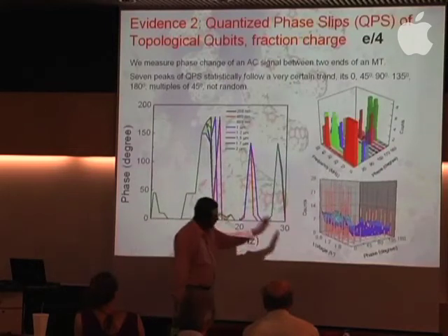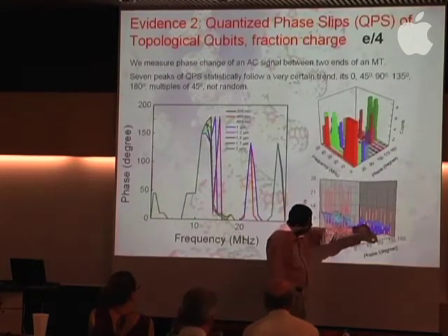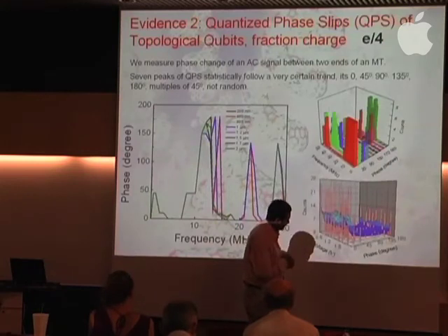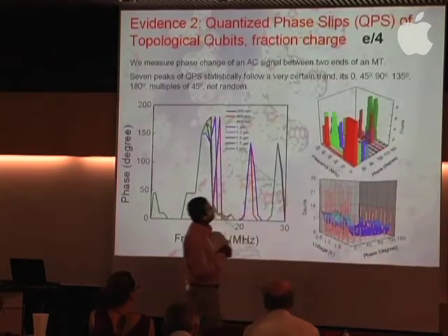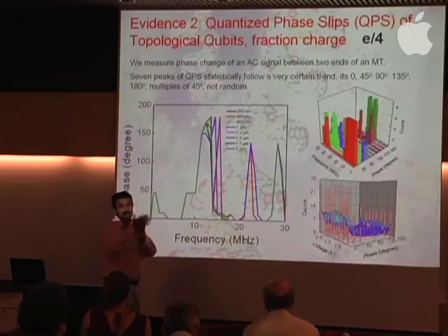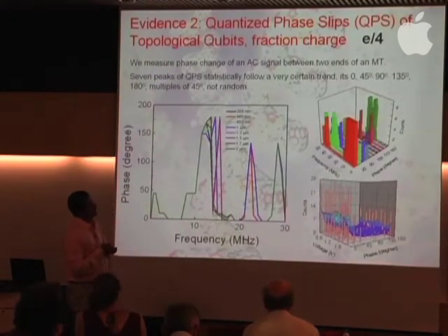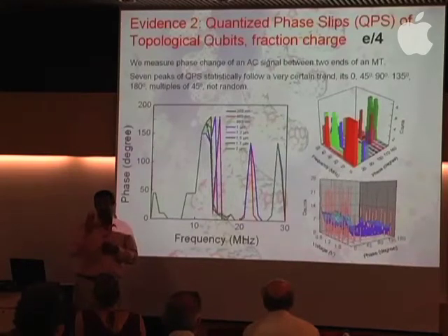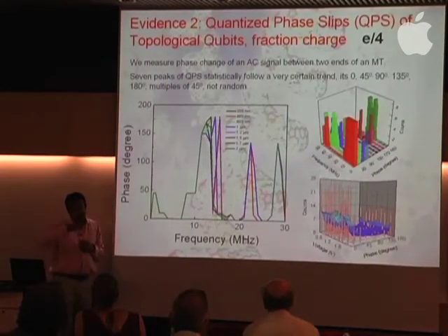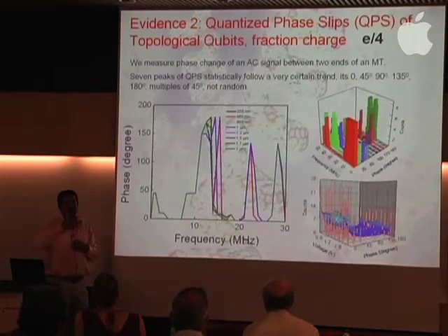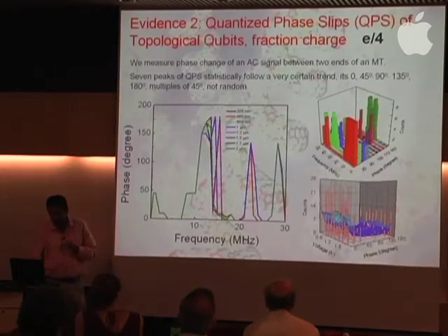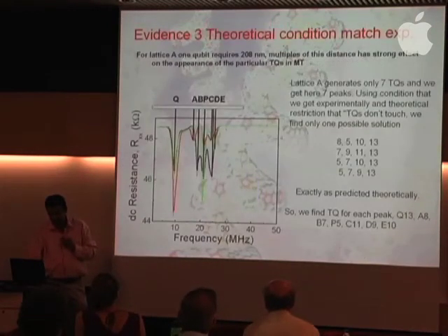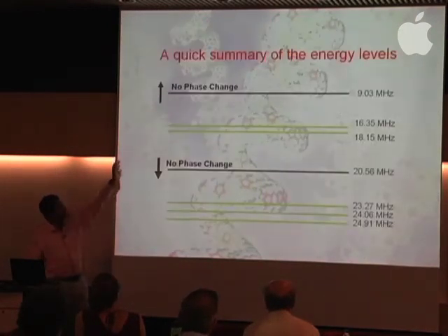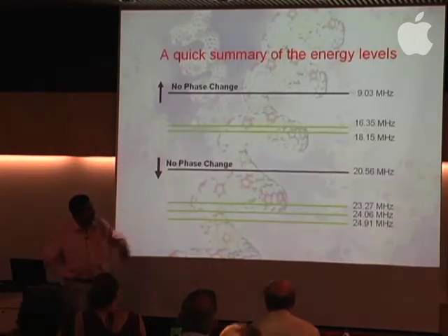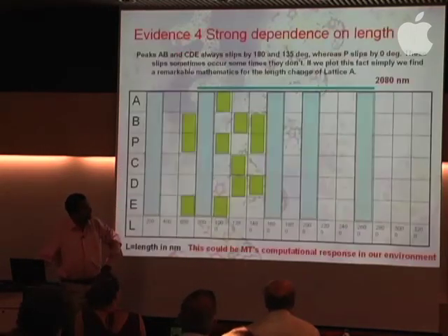And statistically, we find that at very particular points we get a statistically larger number of peaks, near 0, 45, 90, 135, 180. That means basically 4 gaps we can create, phase gaps. So electronic charge e by 4. So that means our resistance will be around 50K, because I showed you the calculation. And phase quantization also proves that there is some quantum effect. So we get this kind of frequency range where we see the peaks.